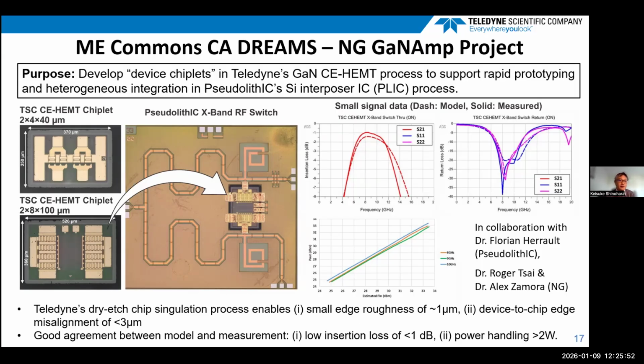And in the middle, I forgot to mention one thing. We use the dry etch chip singulation process to fabricate these chiplets. This process enables a very small edge roughness of as small as 1 micron, and device to chip edge misalignment is less than 3 micron. And these chiplets were integrated through the silicon interposer, which is shown in the middle.